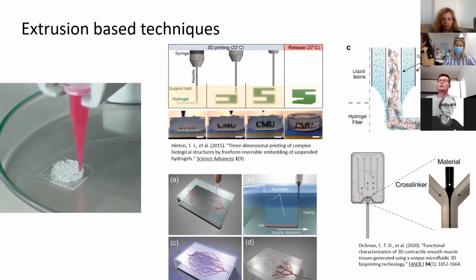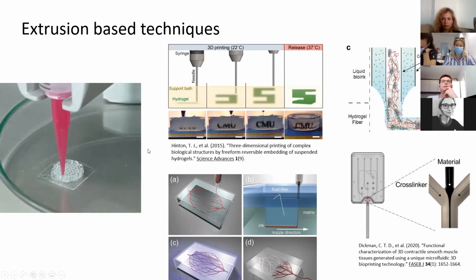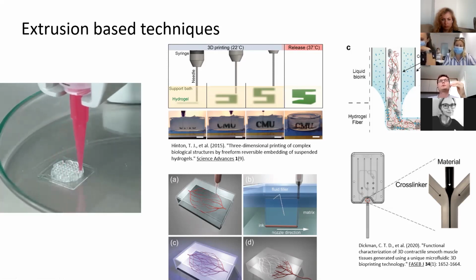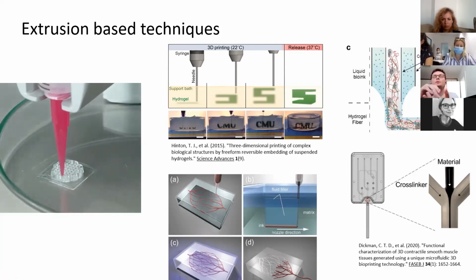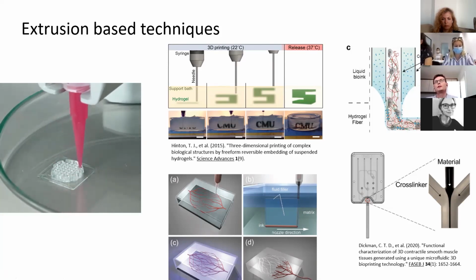But with new approaches, you can also make very interesting structures. So for example, an interesting technique is the so-called FRESH technique, which stands for free-form reversible embedding of suspended hydrogel. So basically what happens here is you deposit material into a support bath, and even if the material itself wouldn't hold its weight to be stable, like you see it here in the video, the support bath keeps the material stable until it cross-links and is stabilized another way, and then you can get the scaffold out. It's also suitable for making really complex geometry, with overhangs, for example.